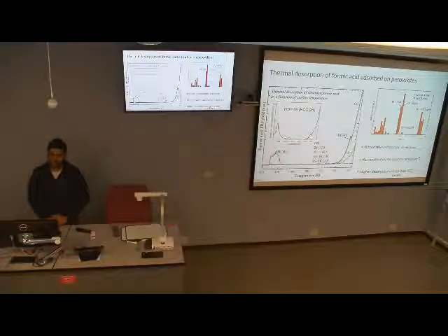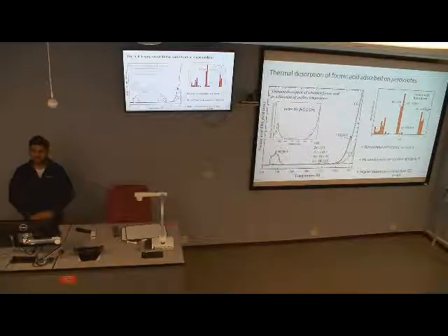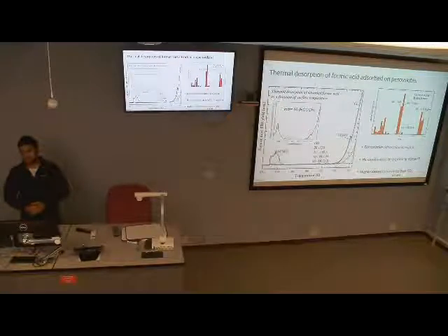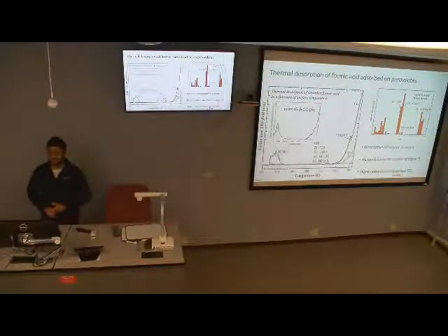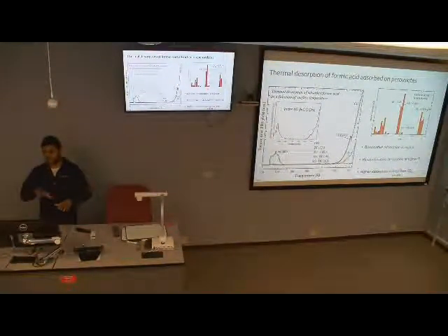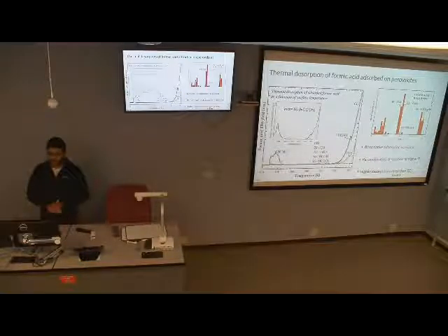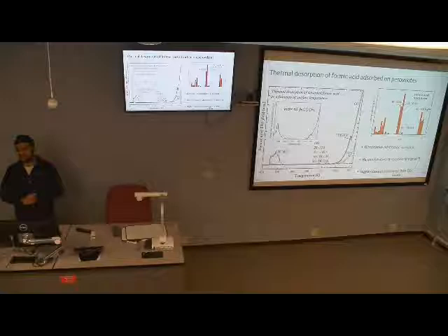Okay, so there might be a molecular precursor for the dissociation, I guess, because you see the molecular peak, right? But I guess the dissociation must happen before 200 Kelvin or something, and those fragments adsorb on the surface in the submonolayer range. So below the monolayer range, it has a high binding energy, so it needs high temperature for the desorption.